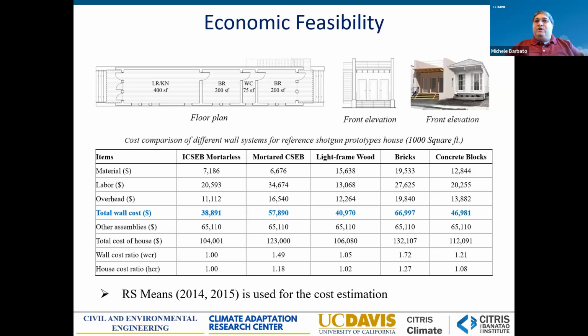But we developed a technology based on interlocking blocks that can be done without having to use mortar to transfer the lateral loads across the different blocks. And we compared the cost of this new technology, the interlocking compressed and stabilized blocks without mortar, the ordinary CSEB with mortar, light frame wood construction, which is typically what is used in 95% of the housing in the US, and then fired clay bricks and concrete blocks.